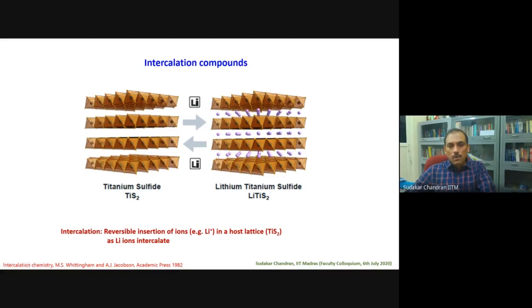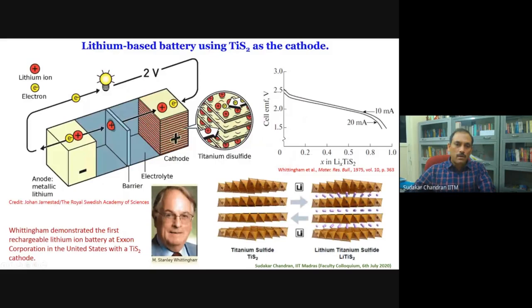Of course, as you fill up lithium into these host lattices, the conduction band gets filled up with electrons as well. So with this as the cathode, Stanley Whittingham demonstrated the first rechargeable lithium ion battery when he was at Exxon Corporation. And he used titanium disulfide as the cathode and metal lithium as the anode, with a lithium perchlorate based electrolyte. And this particular battery gave 2 volts.